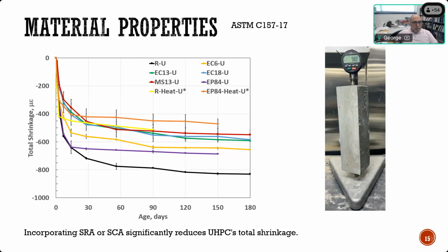You can see that the black line here shows a shrinkage that goes up to 800 microstrain, which is pretty much a high level. But when you use different types, I'm not going into details of what these products are, but these are different products of shrinkage reducing admixture or shrinkage compensating admixture at different dosages, and it shows you can get it basically to half of that amount if you use the right material and the right dosage. And we did that evaluation for the mix developed here in Nebraska to make sure we understand how it behaves in terms of shrinkage.